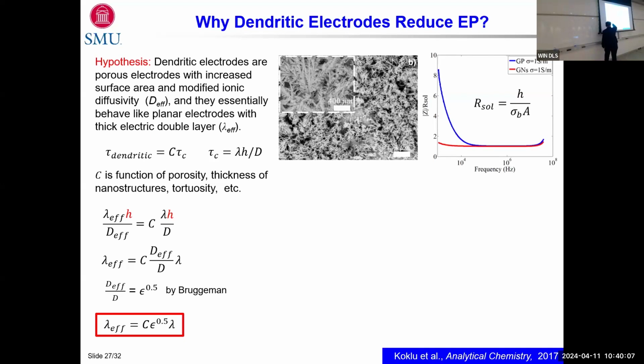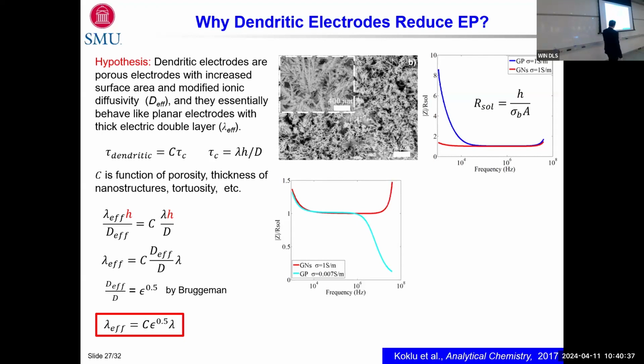Then you have a way of saying that the diffusivity of ions in a porous media normalized with the diffusivity of ions in a regular media is where it comes. And we found that in porous media theory, Bruggeman came up with this correction, and epsilon is the porosity of the medium. So from here on, we have an idea of the effective double layer thickness. So here, basically, the red one is the nanostructure.